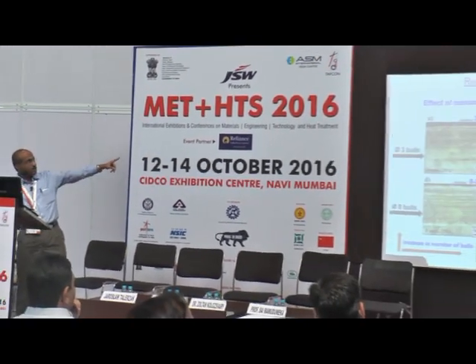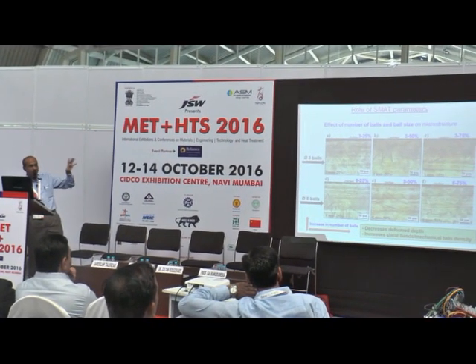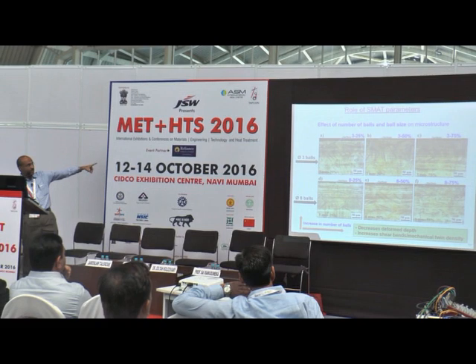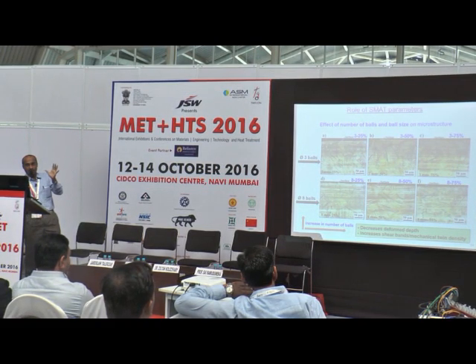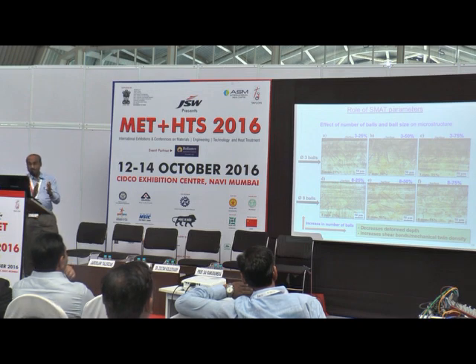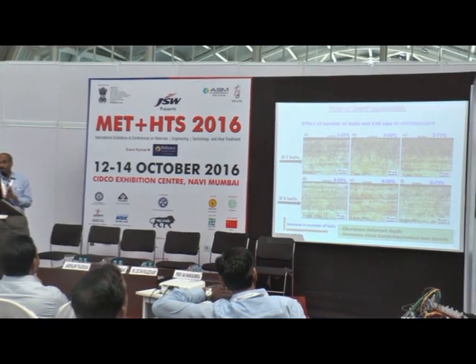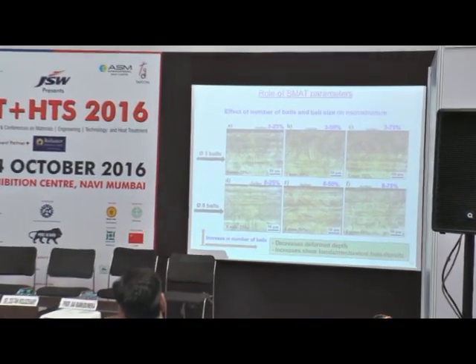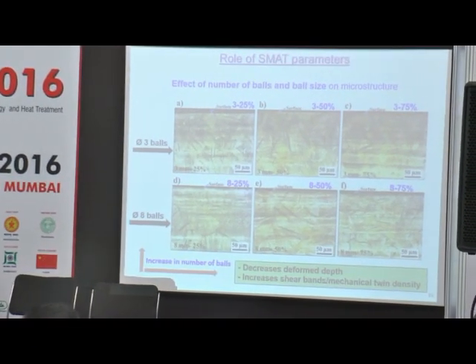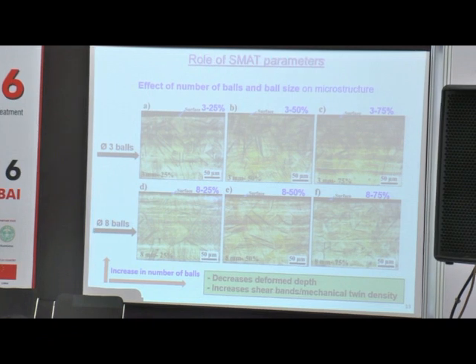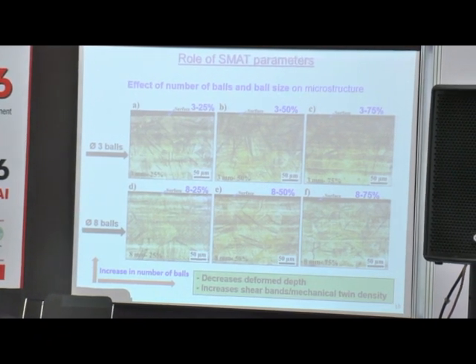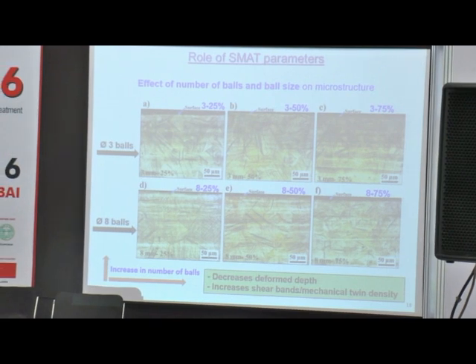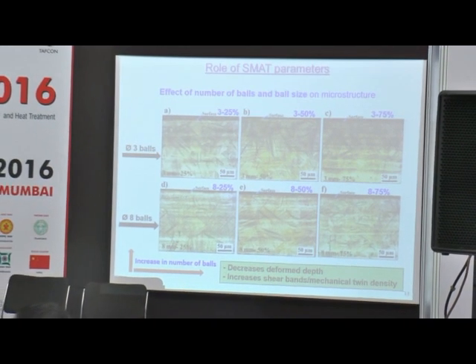If you see from this image to the last image, from the 25% to the 75% balls, you can see the contrast in the etching. At 25% you can still see something there. However, at 75% balls, you can't see anything, even though we applied the same etchant for the same duration. What does that mean? It means the surface is attacked more by the etchant. That means I have more mechanical twins on the specimen surface. At the same time, the spacing between the mechanical twins also increases. It means that the amount of deformation at the specimen surface increases as the number of balls increases, and that plays a role in the amount of martensite in the specimen surface.